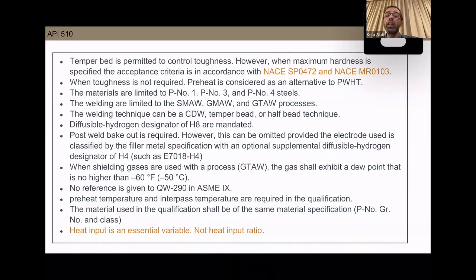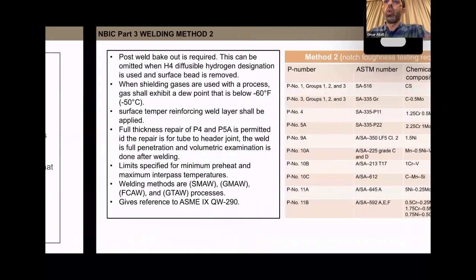So heat input is an essential variable, not heat input ratio. What they are doing is controlling the heat input of each layer to be followed as per the WPS qualification. But since they have not given a requirement or reference to QW-290, you cannot ensure that you are controlling the heat input ratio, because they don't give a reference to QW-290 for temper bead welding.